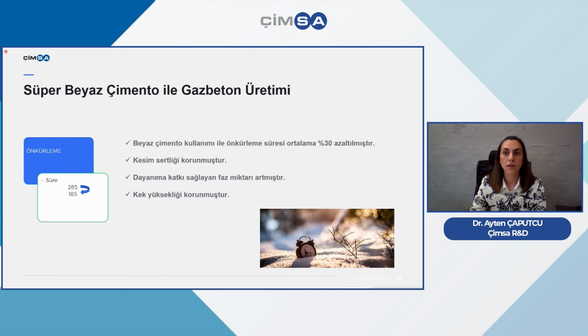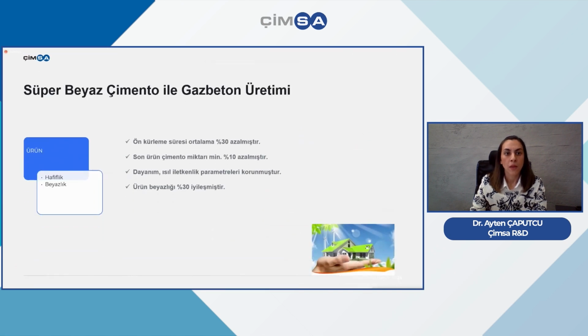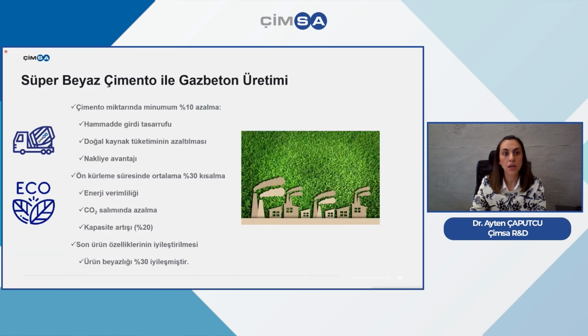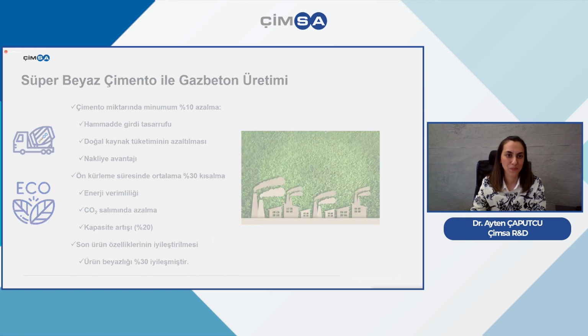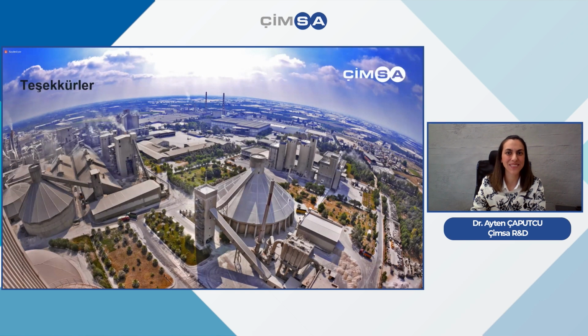We said the preliminary curation period was reduced around 30%, and the amount of cement overall was reduced by 10%. And the resistance and thermal conductivity parameters were preserved. And the whiteness of the product was increased around 30% as well when using white cement. Together with the reduction in the period for preliminary curation, we have improved results for environmental factors as well as emissions. So as a result, preferring white cement instead of Portland cement for AAC production seems to be a very advantageous and lively alternative.